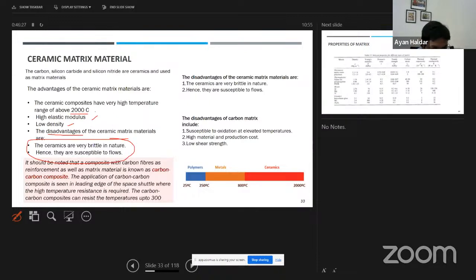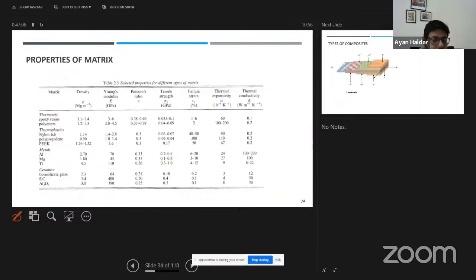So it should be noted that for the composite with carbon fibers, as I was saying, carbon can be used both as fibers as well as matrix. So it's called carbon-carbon composite. Now, in many of the space applications, you might find its use. Carbon-carbon composites have been seen at the leading edge of the space shuttle, where high temperature resistance is required. So the carbon composites can go up to about 300. So I think even more. Yeah. So I think there are some ceramics which can even go more than about 2000 centigrade, and therefore they can be actively used in different applications. So these are some of the properties.